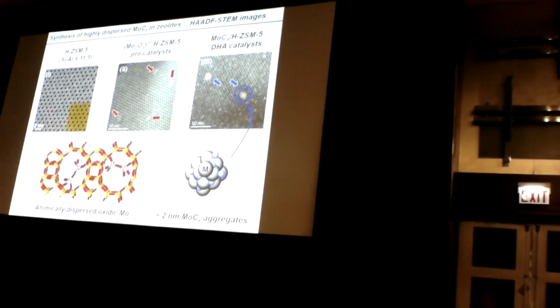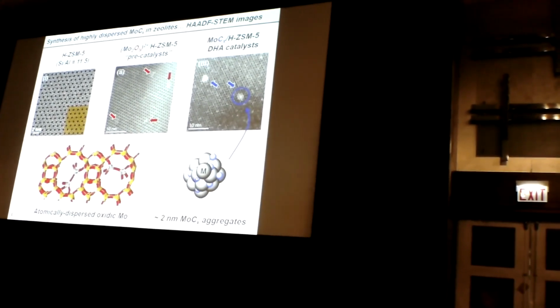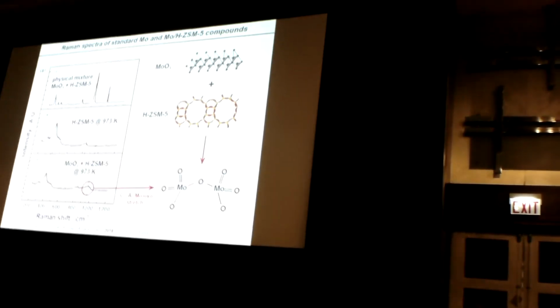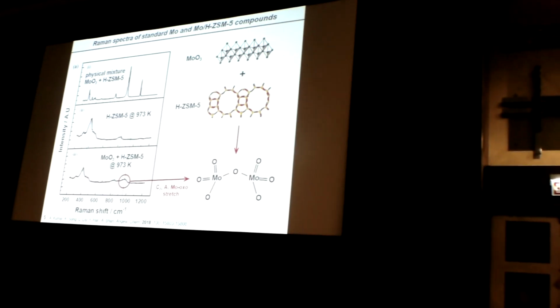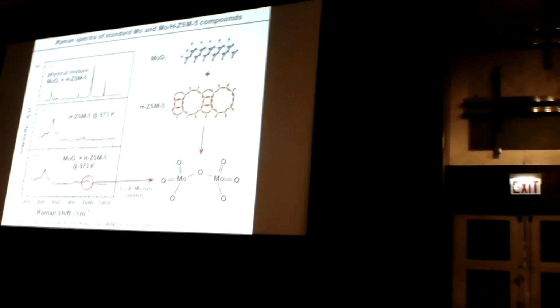I can't tell you this is all the molybdenum in the catalyst, but there are at least some larger molybdenum carbide moieties that are formed during catalysis. So I do see a transformation between the oxide to this carbide. I see, again, spectroscopic signatures in the Raman. This Mo=O has a very distinct signature, which you can see in the Raman if it's dispersed as such, and then is carburized, then this signature band of this Mo=O disappears, again evidencing this transformation of this moly oxide pre-catalyst.